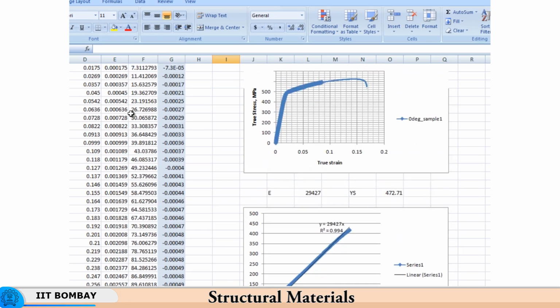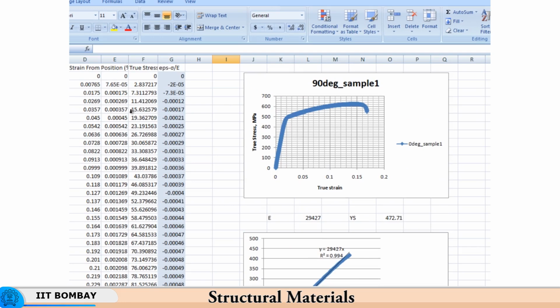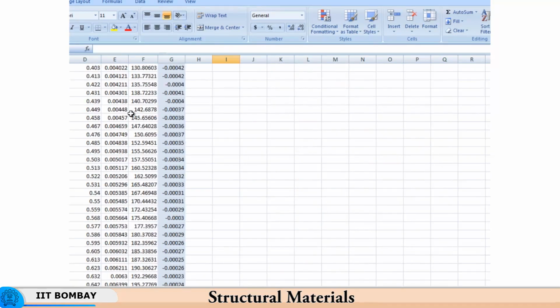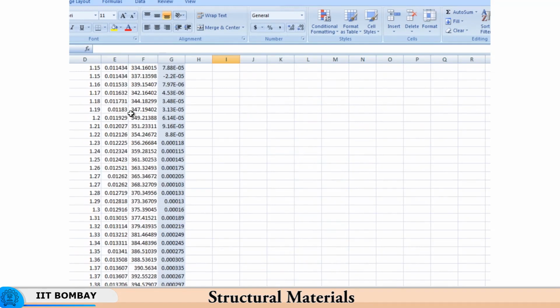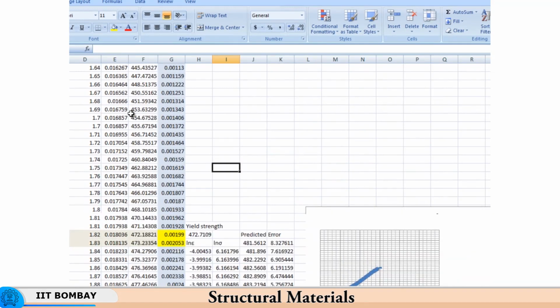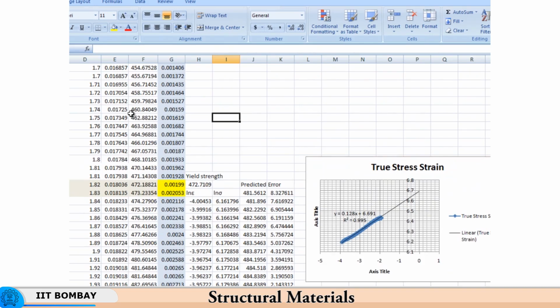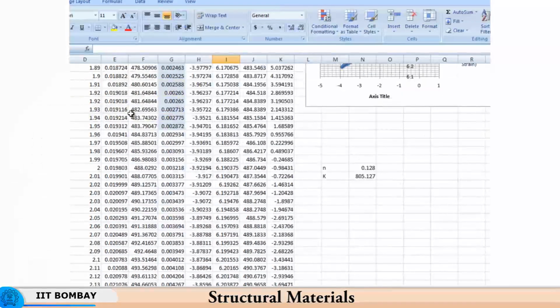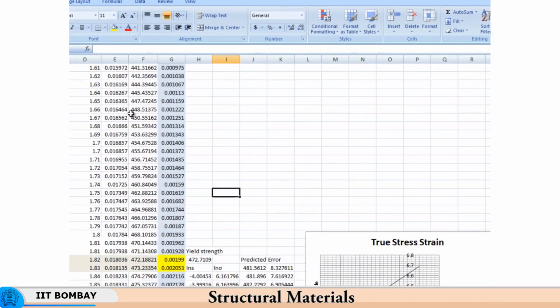So, now this is the parameter which I have plotted for the stress strain curve. So, you have in the elastic range epsilon minus sigma by E, and then this keeps on increasing. Now, this is the third decimal here, and you see that it has reached 0.00199. So, 0.002 and less than 0.002, here is slightly more than 0.002. Then I interpolate between these two values, and I have my yield strength as 472.71. And from this point onwards I start applying my plastic deformation formulae.